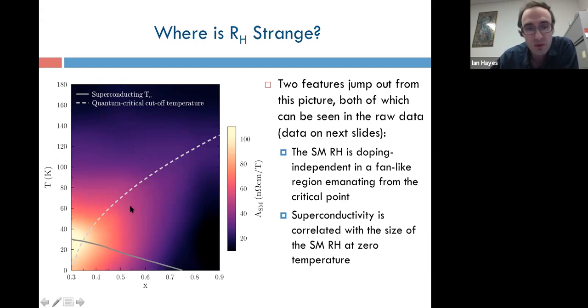When you cross that fan-like region, the strange metal field dependence weakens, and it continues to weaken, but it doesn't weaken all the way to zero at zero temperature. There's an extended range over which you still see a decreasing RH with increasing field, and it's strongest near optimal doping, and it decreases for higher phosphorus content, and then vanishes at the same point that superconductivity vanishes. So if you go just beyond the superconducting dome at low temperatures, you see none of this decreasing RH with field, you see pure H squared. You can recover the decreasing RH with field if you go to higher temperature, but specifically the low temperature part of the Hall coefficient seems to be strongly correlated with superconductivity.